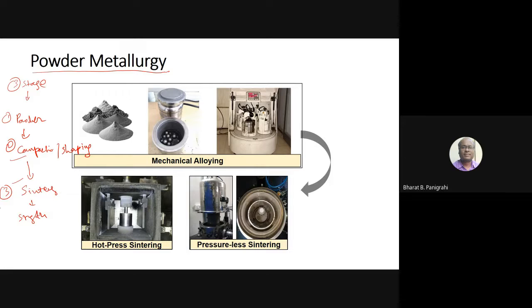When we talk about powder, it can be prepared through various techniques. You may be familiar with atomization techniques, and there is another technique called the mechanical alloying process. For high entropy alloys, most of the reported powders are prepared through mechanical alloying. In mechanical alloying, you have all the elemental powders A, B, C, D. You take them in the appropriate composition. Do you want equiatomic or a different composition? You play with the composition, which fraction of which powder, which element you want, and how much.